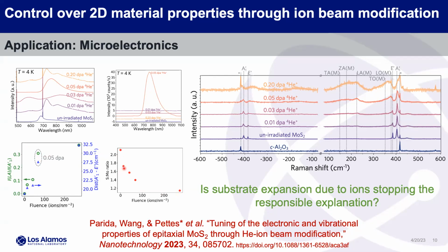So we don't know really what's going on with that, but we do know that you have some synergistic effects. And so we said, let's use this to show that we can do this type of material modification. We have control over it. You can see how nice this trend is. But when we're talking about modifying the material's properties for doping, let's try to get some follow-on funding to do doping as we go to even lower energies. This is at 50 kilo electron volts, but we want to go even lower. And so we're looking for investment; the CHIPS and Science Act is a small part of it.